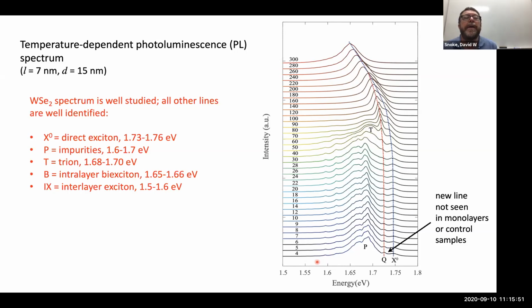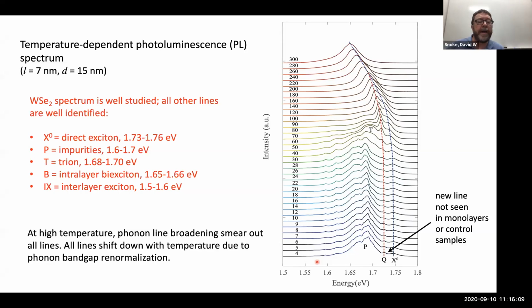And so essentially the overall strategy is, we'll first look at monolayers and see what we see there. We make the bilayer and ask, what's new? Okay, there's only 2 new things. One is the indirect exciton that we already know all about, and the other is this Q line. Unfortunately, at high temperature, they all sort of smear in, although you can see there's still sort of a double bump structure going on there.